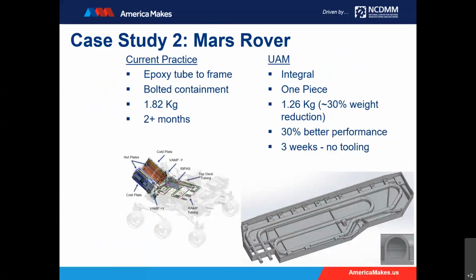A second kind of case study was a part that was made for NASA JPL under a Phase 2 SBIR. This part was intended for the Mars rover. Unfortunately, we didn't quite get done in time, but it's a good educational case study. The part that flew, the part that's on Mars today, was built by taking an aluminum CNC milled plate and then epoxying on stainless steel tubing. So you can imagine the epoxy gives somewhat of a thermal break, as well as adding a considerable amount of weight, as all those tubes also were bolted with saddles.